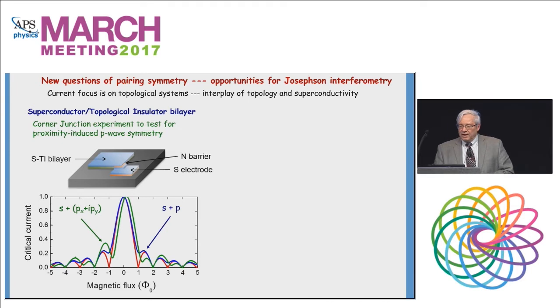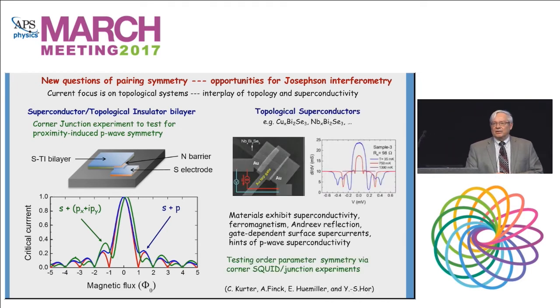Another experiment is to look at a class of materials that are thought to be topological superconductors. Candidates for this are things like copper-doped bismuth selenide and niobium-doped bismuth selenide. These are transport measurements from our group that show Andreev reflection. These materials show superconductivity. They show magnetism. They show Andreev reflection, gate-dependent surface currents, and hints of p-wave superconductivity in the tunneling spectra. We're right now trying to test the order parameter, doing a corner SQUID, corner junction experiment to see if these have a p-wave or odd symmetry type of order parameter.